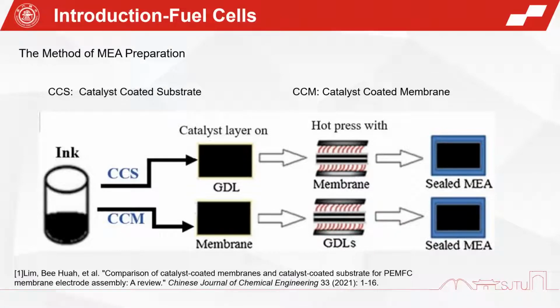For the MEA prepared by the CCS method, the interface between the cathode layer and the electrolyte membrane is not in close contact, giving high interface resistance and resulting in a relatively low output power density of the fuel cell. The CCM method can effectively improve the rate of catalyst utilization and diminish the interface resistance between the proton exchange membrane and the cathode layer, obtaining high output power density compared to the CCS method, and thereby it has become the mainstream approach for preparation of the MEA for low temperature PEMFC.